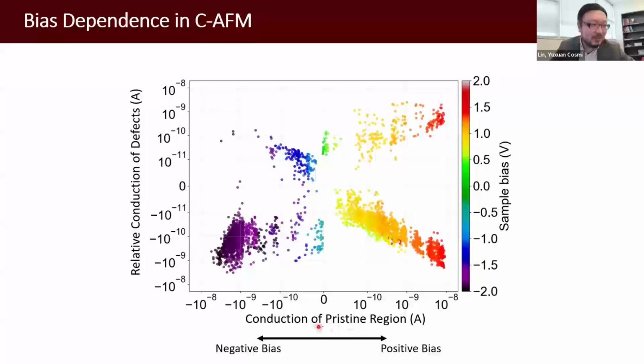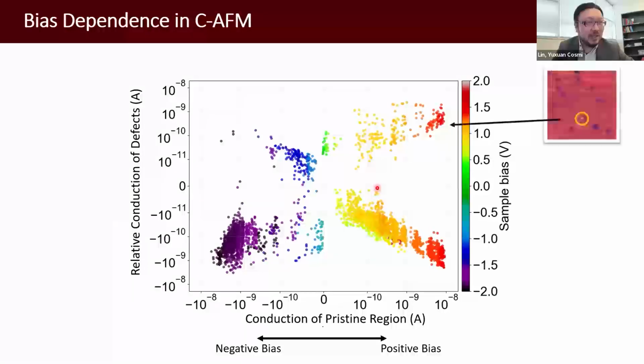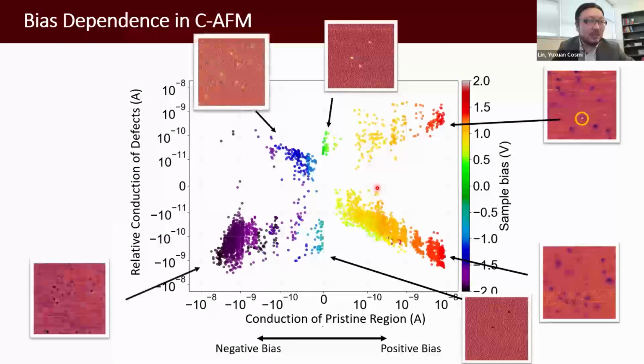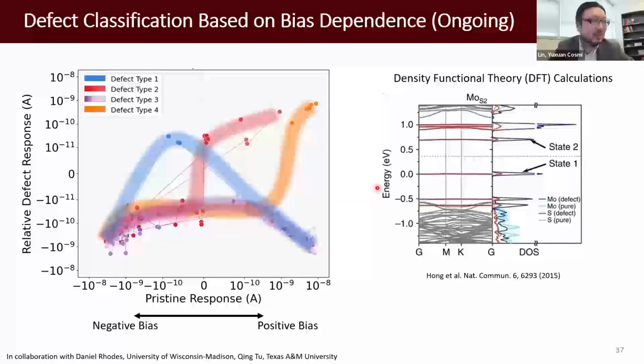So the x-axis is the conduction along the pristine region, equivalent to the bias, and we use the current difference we measured on the defect site versus pristine to categorize the intensity of those defect features in the conductive AFM. You can see a very complicated mapping, and they are related to different defects at different spatial locations on the sample. My students were working hard to align those frames so we can plot the behavior of individual defects. And right now, this is still ongoing.